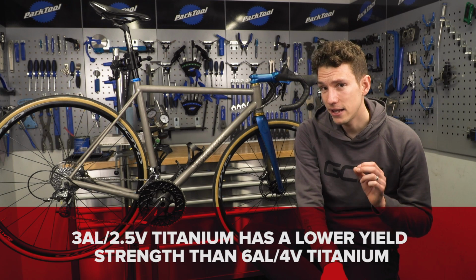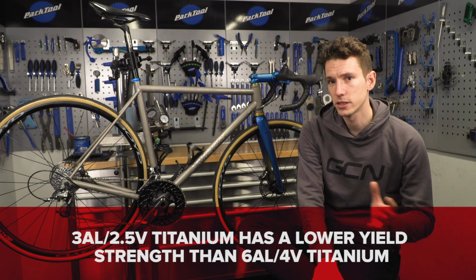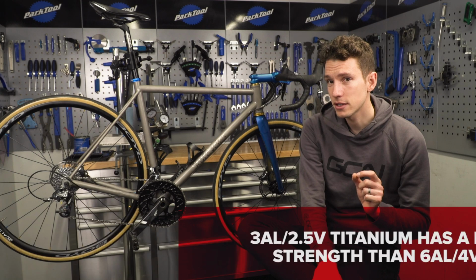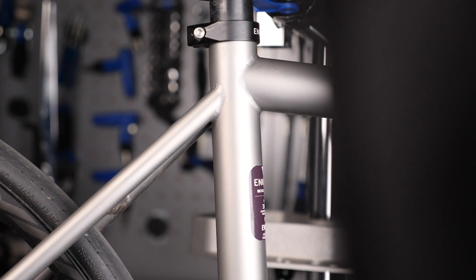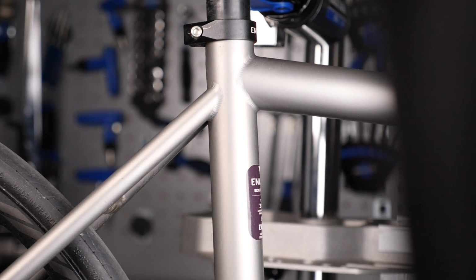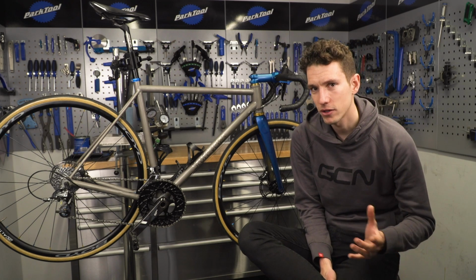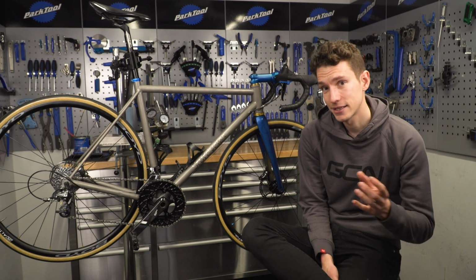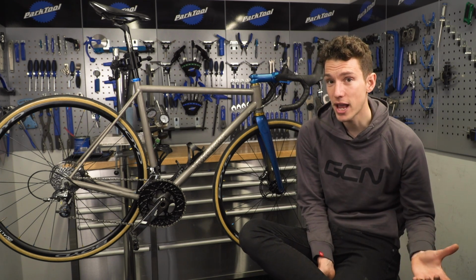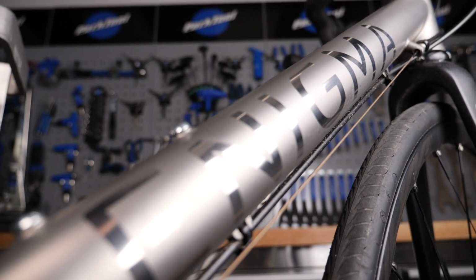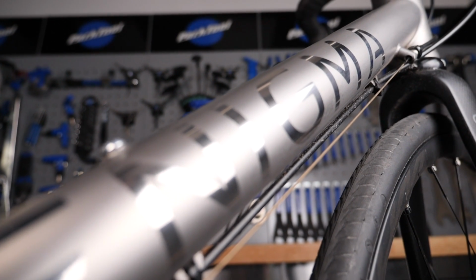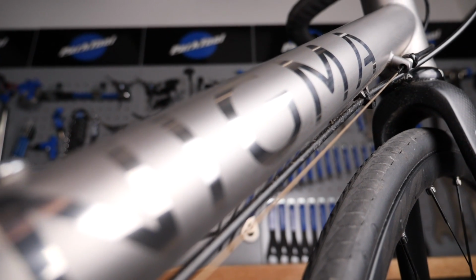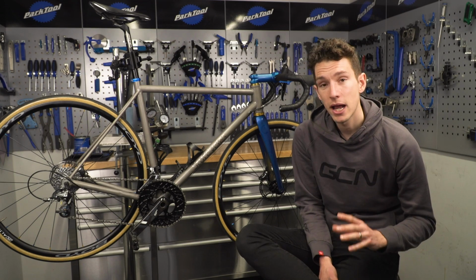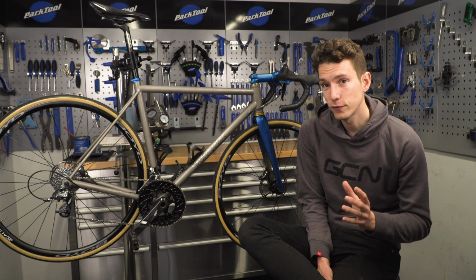3,2.5 actually has a lower yield strength than 6,4 titanium, but then that's one of the reasons why it is used almost exclusively in bike building, because 6,4 titanium is incredibly hard to work with. It's more brittle and less ductile, so forming it into simple shapes, like, I don't know, tubes for a start, is incredibly hard.